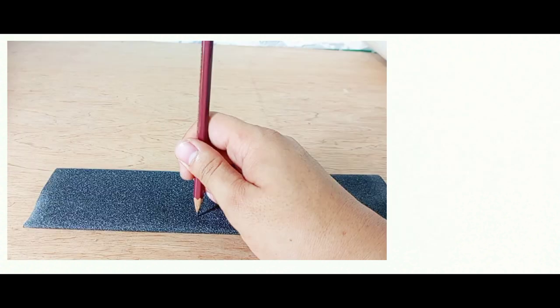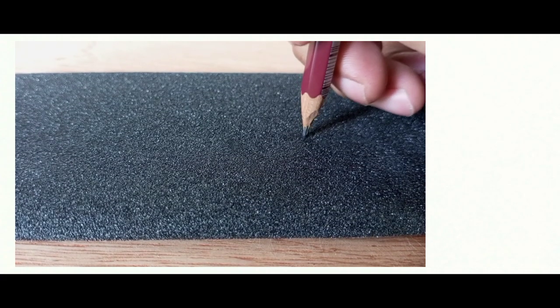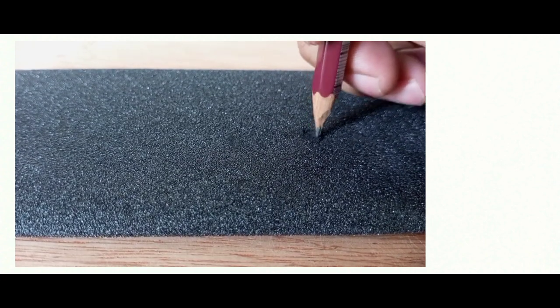Next, hold the pencil at 90 degrees to the abrasive paper provided. Sharpen the pencil to have flat tip with sharp edge.